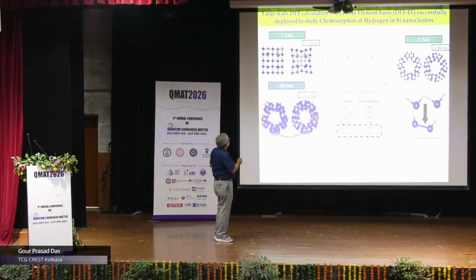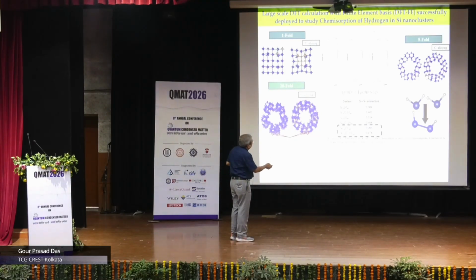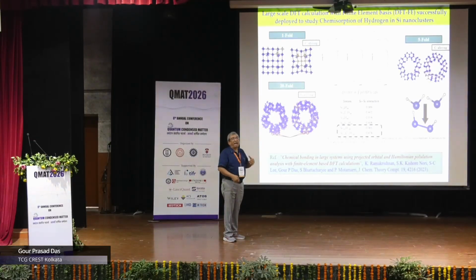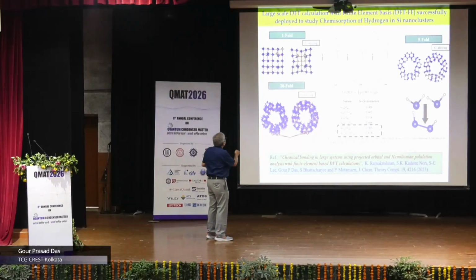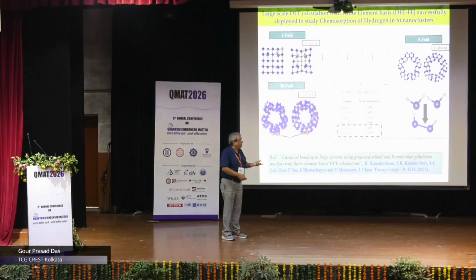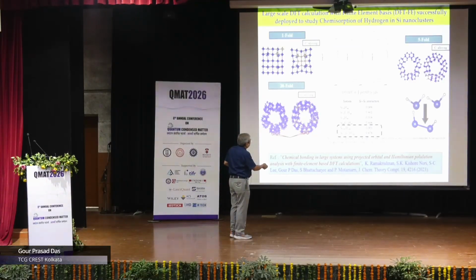And what will happen is that the hydrogens all around, and the silicons on the outer side, will get affected by this carbon alloying in such a way that hydrogen-hydrogen dimer formation will take place. And it will take place more and more if you increase the size of the silicon carbon nanocluster. If you take this as a motif, make it one-fold, two-fold, five-fold, 10-fold, 20-fold. I have not shown all. This is a 20-fold version, so this is 20 times this. So naturally, you can see the number of atoms becomes huge. And look at that: Si120, C25, H150.